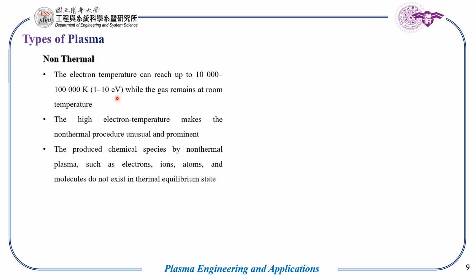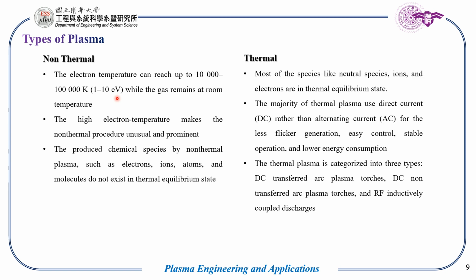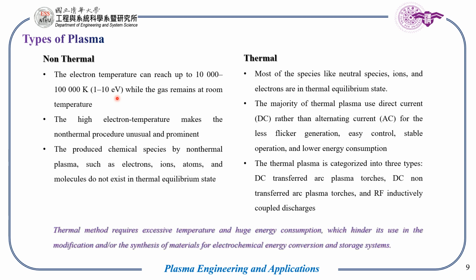So this plasma can be created in different ways. It can be classified into two: thermal and non-thermal. In the non-thermal case, the electron temperatures can reach up to 10,000 to 100,000 K, while the gas remains at room temperature, which means we need not use any high temperature in this case. The high electron temperature makes the non-thermal plasma unusual and prominent. In the case of thermal, we need to use energy as well as heat, and the temperature needs to be very high. So in commercialized tests and also in many different research industries, thermal methods are not used, and they normally use non-thermal ways to generate the plasma.